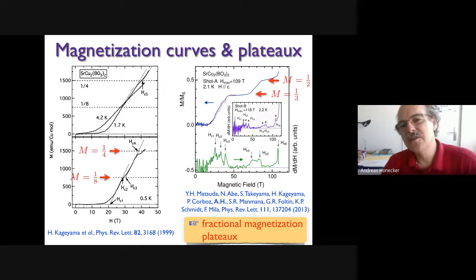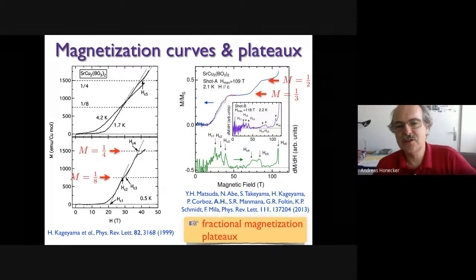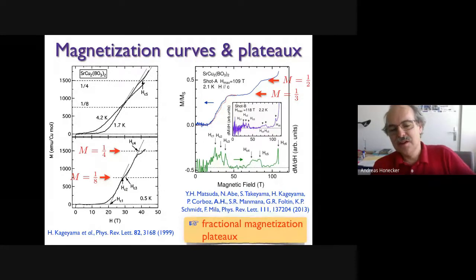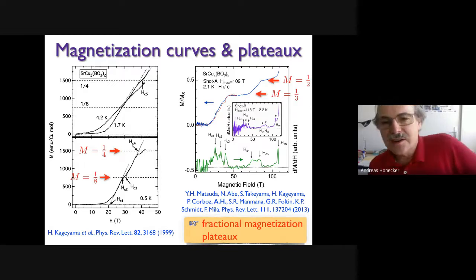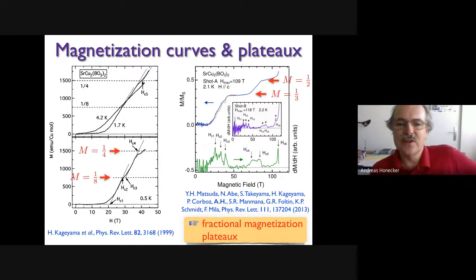On the right, there's a more recent plot for strontium copper borate, for the magnetization curve of strontium copper borate. Well, that is work that I happen to be involved in, and that is a magnetization measurement going up to roughly 110 Tesla. And you have less resolution at low fields here, but you do see two very pronounced plateaus at 1/3 and 1/2 of the saturation magnetization.